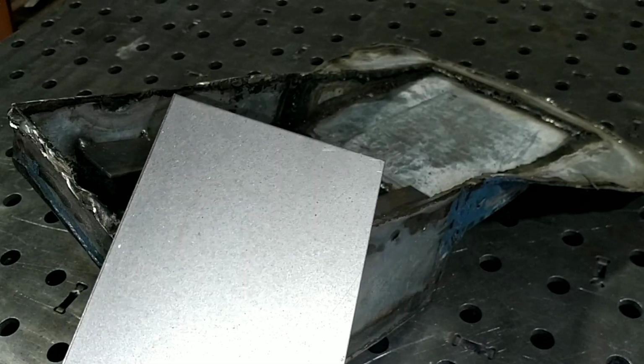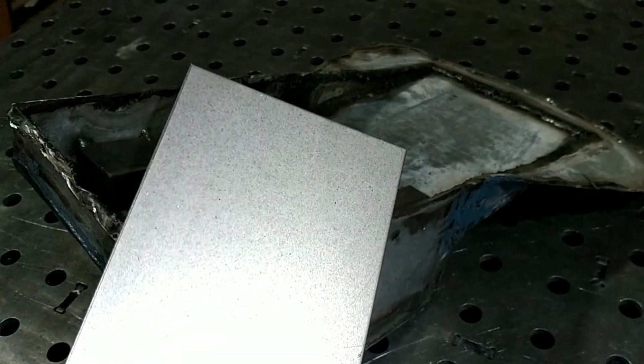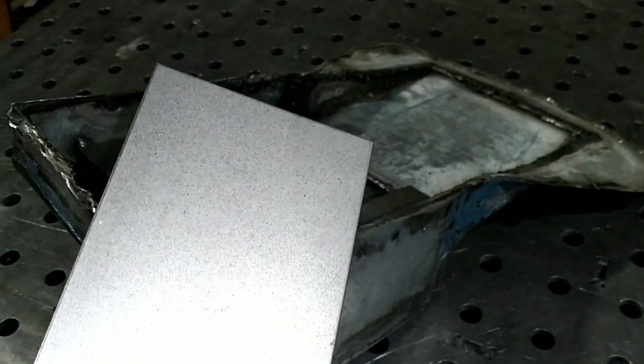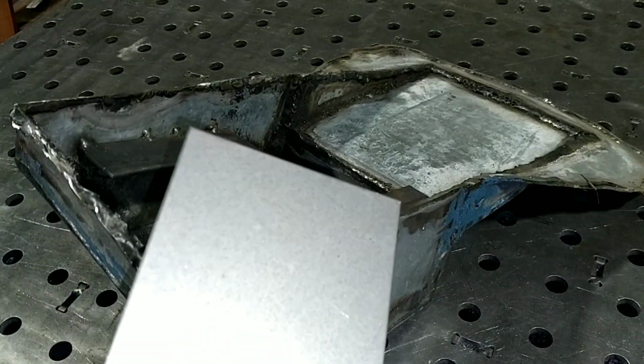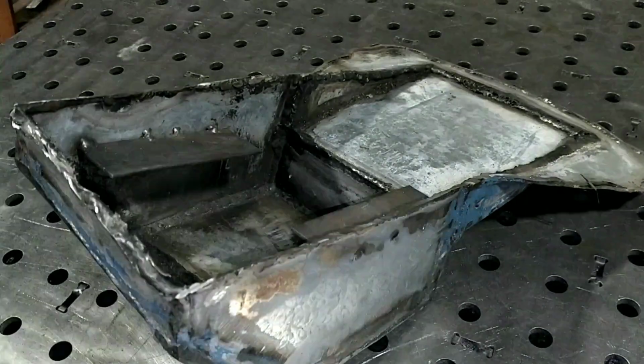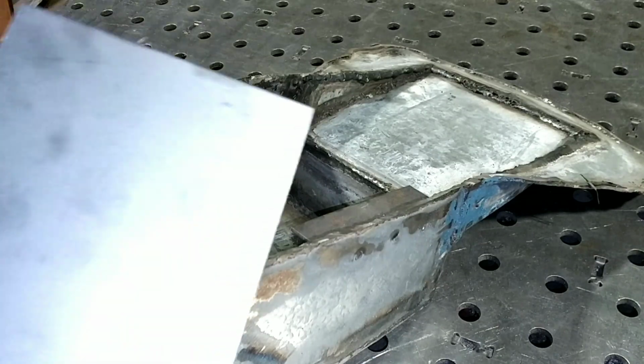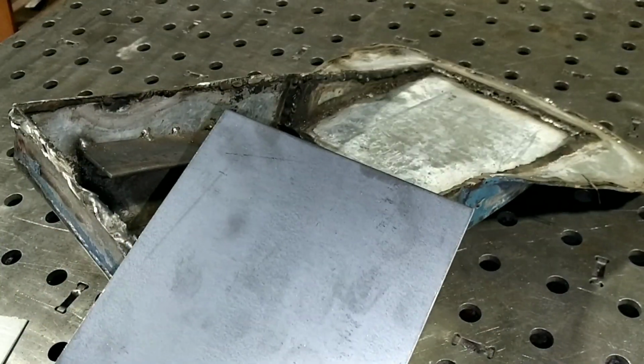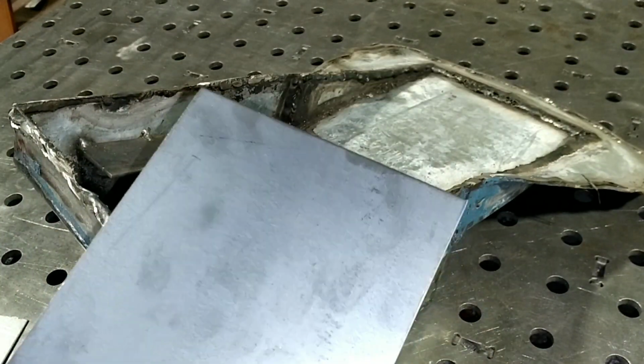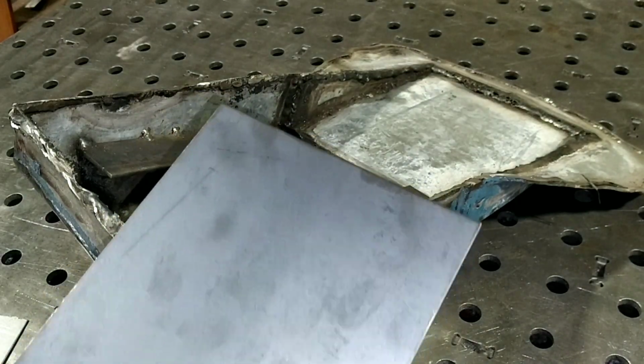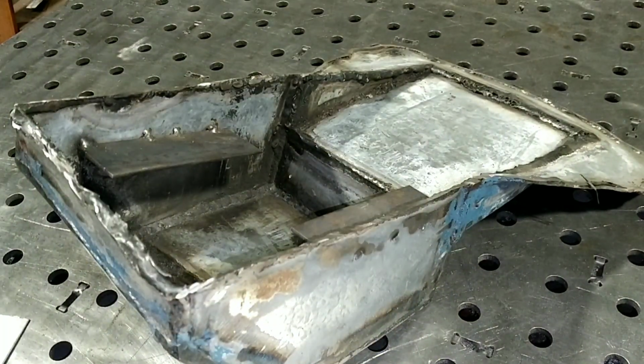The downside is it rusts like you wouldn't believe. Your fingerprints will show up a couple of days later if you leave it out and exposed. So it always has to be heavily oiled, heavily cleaned, then welded. The reason I used hot rolled on the other piece is mostly material thickness. I wanted a nice thick sump. So this is 2 mm, where the thickest you can get in cold rolled is 1.1. So we're nearly 90% thicker with the hot roll.